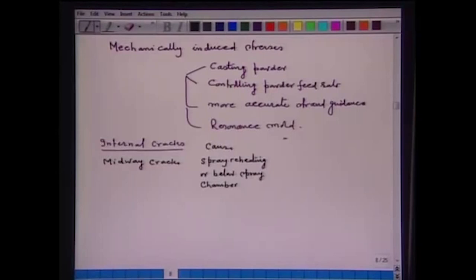So, the strand gets reheated because the heat from inside of the strand is coming out, and when it does not find any water, the top of the strand can be heated up. That is called the reheating of the strand. The factors that influence this are the high pouring temperature, or when sulfur and phosphorus is greater than 0.02%. What is the remedy?